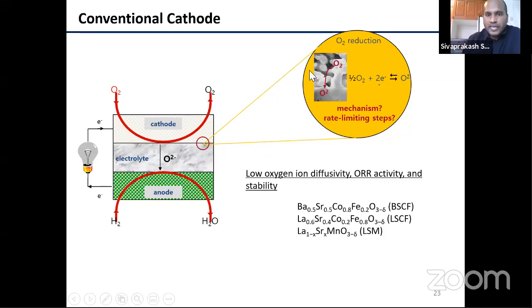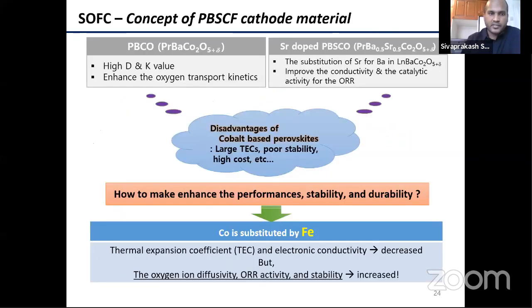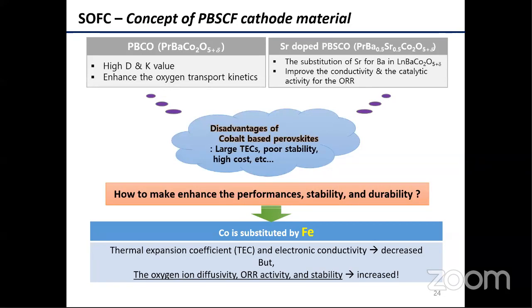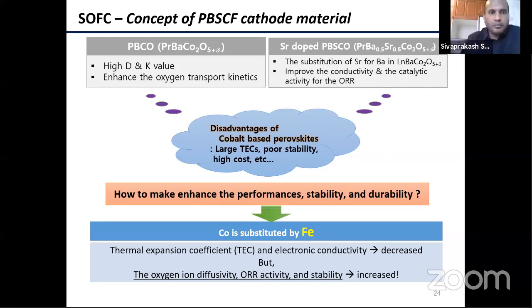So we need to find a better cathode that works well for the oxygen reduction reaction at lower temperatures, between 700 and 800 degrees Celsius. For this, we first developed a layered perovskite material, praseodymium barium cobalt oxide, a layered perovskite material.